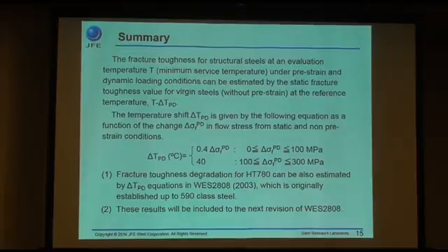Okay, let me summarize my talk. The most important is the reference temperature concept. And this difference temperature concept, the delta TT, that is the transition temperature rise, is needed. And also this transition temperature rise is related to the flow stress change, because the flow stress change can be easily evaluated by the empirical formulation.